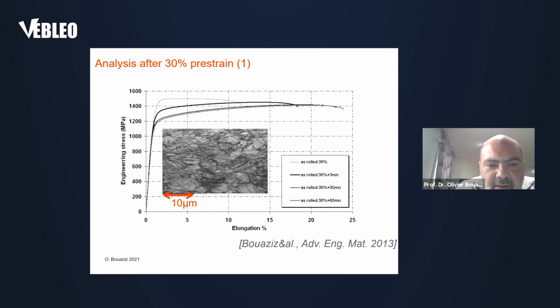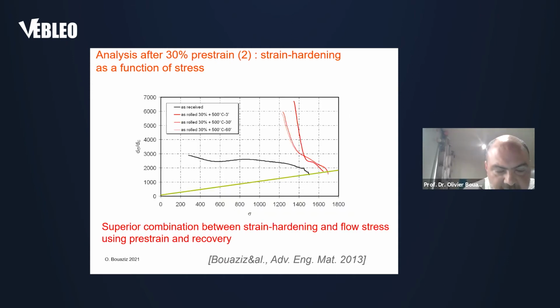So this graph shows that the YS decreases just a little bit, but you recover the strain hardening after the recovery treatment. To analyze these results, it's beneficial to draw the strain hardening as a function of flow stress. It is the so-called Kocks-Mecking plot.